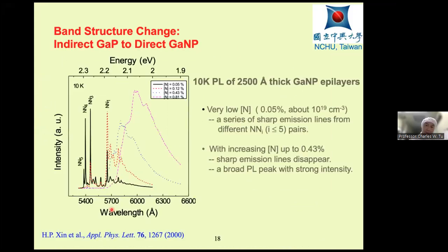So then the third effect is this band structure. Here I show photoluminescence of gallium phosphide with a very small amount of nitrogen. It's in the range of like 10 to the 19 or something, and we see discrete nitrogen peaks.